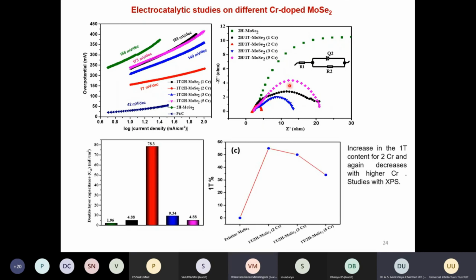So what we see here is the double layer capacitance, which we measure as another characteristic, which tells about the electrochemically active surface area. A higher surface area means that activity is generally better. Here you can see that the 2% doped chromium sample shows a higher double layer capacitance compared to all other samples.